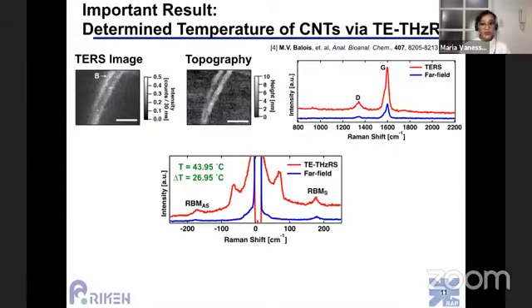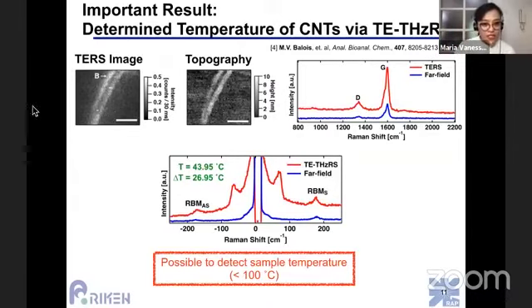Now, as a result, we were able to extract the anti-Stokes and Stokes Raman from the carbon nanotube. And from there, we were able to detect sample temperatures less than 100 degrees Celsius. Now, one thing I have to point out here, since I was so excited about the temperature, is please look at this image over here, which is the TERS image and also the topography image. The other powerful thing about TERS is that you can get both the chemical information and the topographical information simultaneously. And note here that this is actually two carbon nanotubes, and I'm sorry, but the scale bar here is around 100 nanometers. So we can actually see very, very thin carbon nanotubes, both in the TERS image, which is the Raman imaging of the G band, and also the topography.